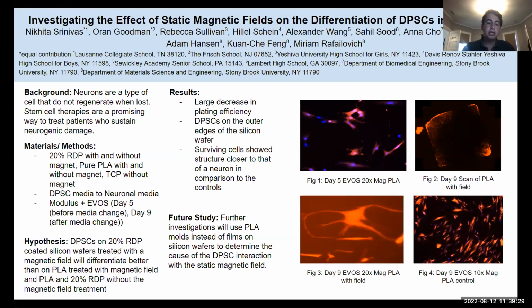So these molds are heat treated just not on silicon. So therefore they don't have the electric charge, and they're stronger. They don't have films that can fall off. So the RDP surface should not degenerate and kill the cells.